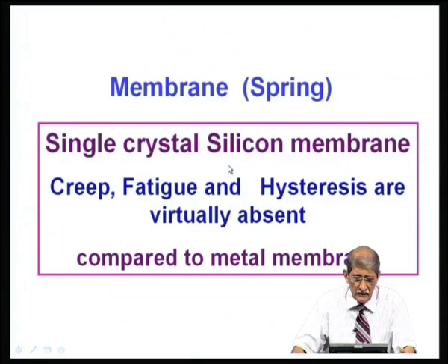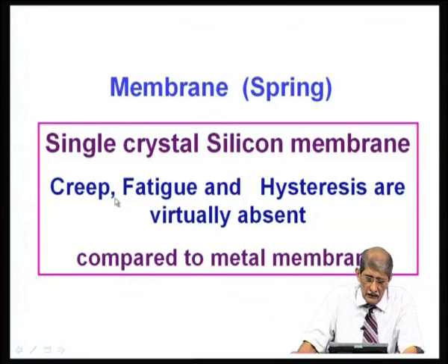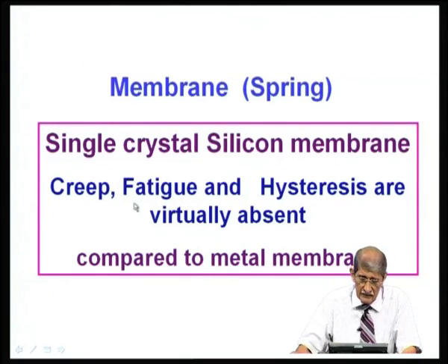So, the membrane, or you can call it a spring also if you like, is usually or invariably made of single crystal silicon material. That is because silicon is a very good mechanical material. It has high Young's modulus, high yield strength, all those advantages are there, even comparable to or better than steel, excellent mechanical material. The added advantage is, unlike some of the metals, metallic membranes, silicon is free of creep, fatigue, hysteresis, virtually free.